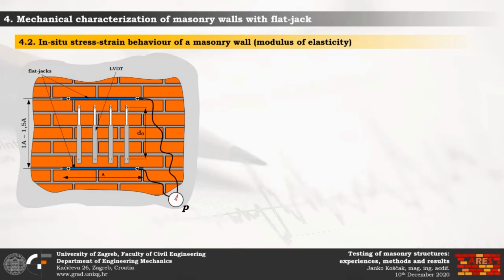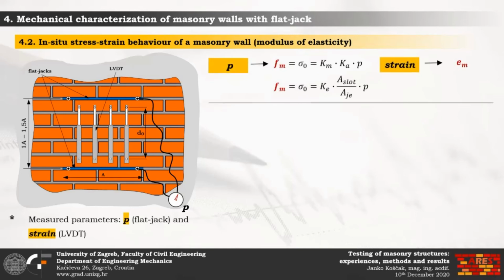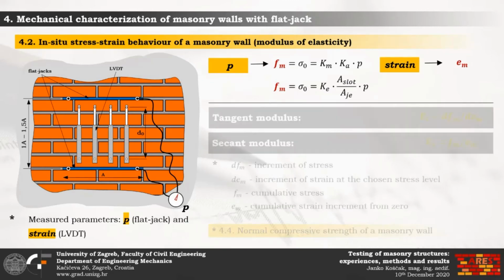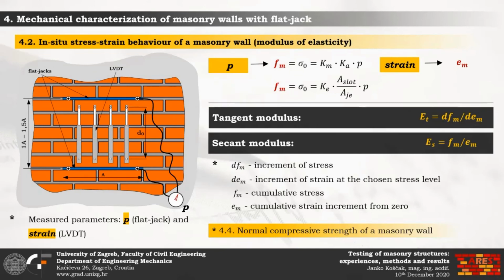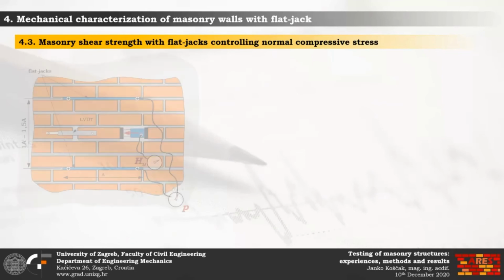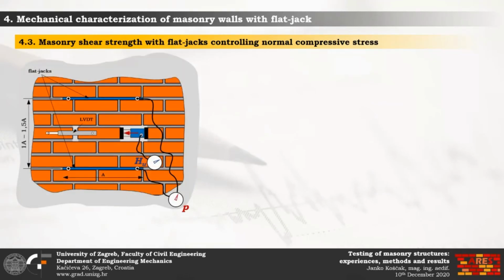Secondly, LVDT sensors for continuous strain measurement are placed vertically between the flat jacks. Now the different levels of pressure should be applied in increments, and the pressure of each increment should be held for about 1 minute. At each increment, strains and pressure are measured, and the normal vertical stress is calculated. Finally, the tangent and secant modulus of elasticity can be determined by dividing the value of stress by the corresponding strain value. The next slide describes the procedure for determining the masonry shear strength with flat jacks controlling normal compressive stress.